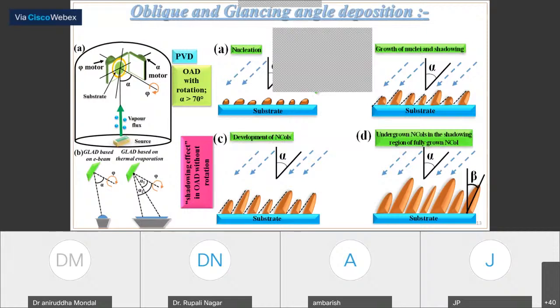Okay, so these are the different fabrication procedures. We can use liquid phase epitaxy, vapor phase epitaxy, MOCVD and MBE techniques, but these techniques are very costly. So we can fabricate this kind of one-dimensional nanostructure by oblique angle deposition. With the help of oblique angle deposition, we can very easily fabricate nanowire structures.